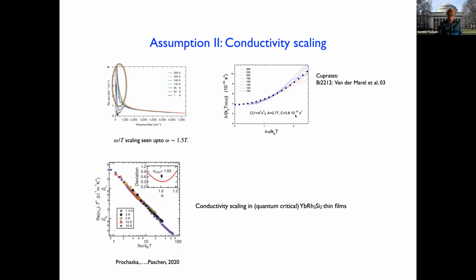And here, what these authors did in 2003 is to make a plot of 1/k_BT times sigma of omega versus the scaling argument, h-bar omega over k_BT. And the data collapse is not great, but it's not bad either. And you see that it fits some sort of data collapse up to about 1.5 times the temperature. Beyond that, you run into this power law tail, which probably has nothing to do with quantum criticality. There's much better data by now. Just last week, there was a nice paper from the Netherlands showing better scaling data for omega over T scaling. But the best data that currently exists is not in the cuprates, but it's in a material called ytterbium rhodium silicide, which is also a strange metal system.